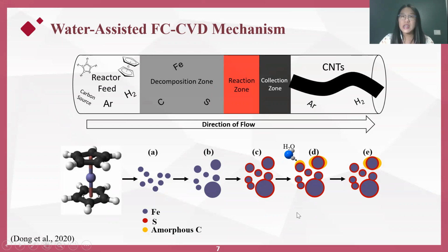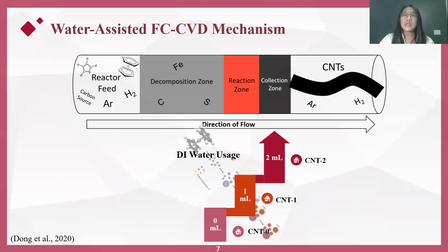Additionally, smaller size CNTs could be achieved with the deionized water as a result of the catalyst size shrinkage. In this work, we have directly included the deionized water into the catalyst solution to provide a more homogeneous and uniform distribution. Based on the amount of water added into the standard catalyst solution, 3 groups, denoted as CNT0, CNT1, and CNT2, were investigated.